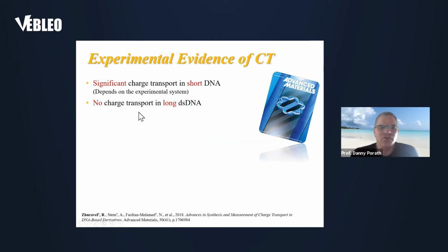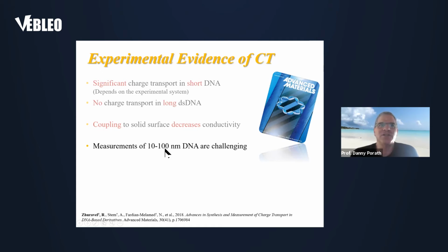But what do we know from the previous experiment? And this was summarized in a review in Advanced Materials that we prepared, cited here at the bottom. And we found first that significant current is transported in short DNA molecules, and that depends on the experimental system. No charge transport was going in long DNA molecules that were deposited on a hard substrate, so the coupling to the solid surface decreased the conductivity, and also that measurements of 10 to 100 nanometer DNA are very challenging.